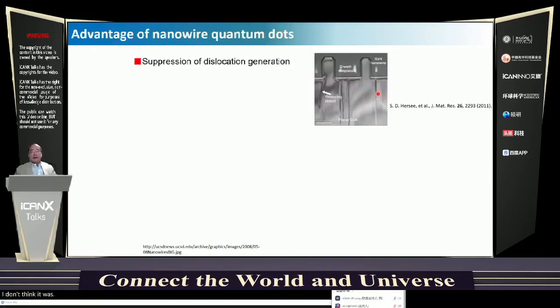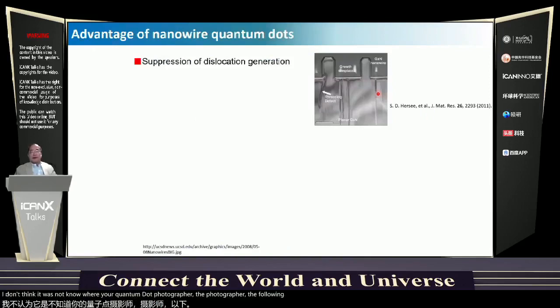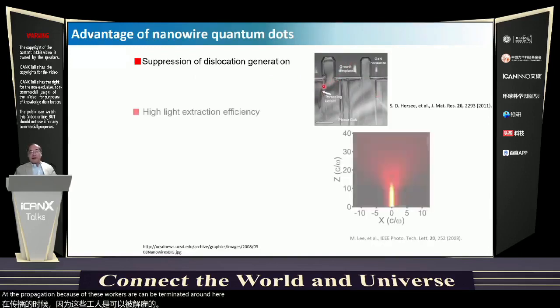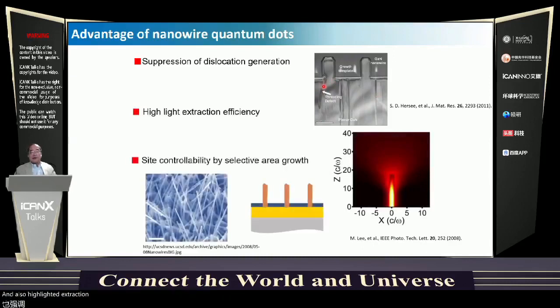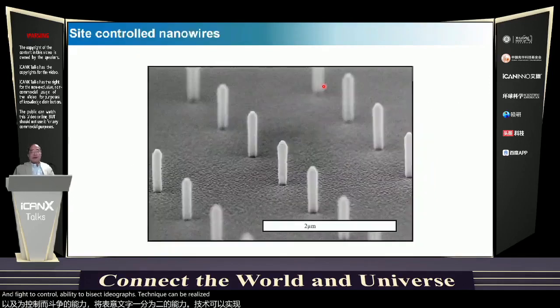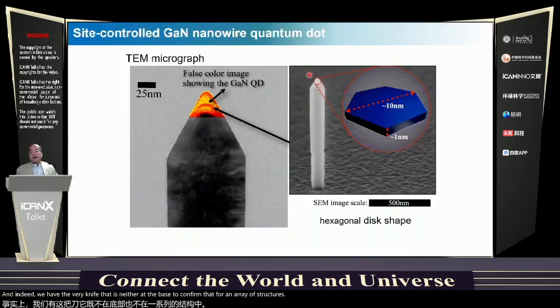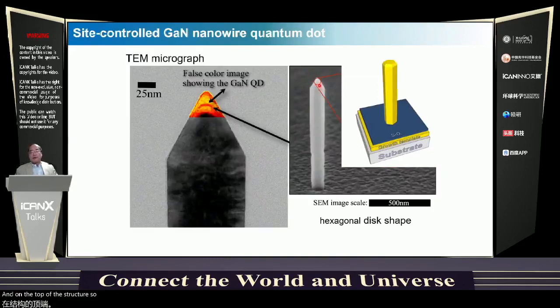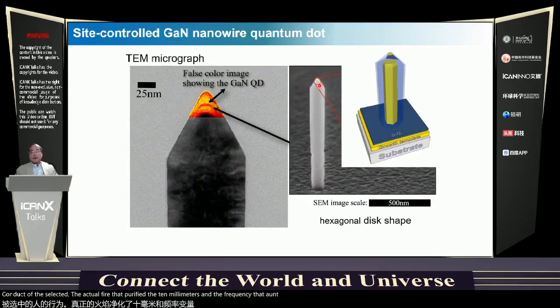So the advantages of the nanowire quantum dot for a single photon source are the following. We can suppress dislocation propagation, because dislocations can be terminated around here. High light extraction efficiency can also be realized, and site controllability by the selective area growth technique can be realized. Indeed, we have very nice gallium nitride-based nanowire structures, and on top of them we form quantum dot structures. The actual lateral size is 10 nanometers, and the thickness is around 1 nanometer.